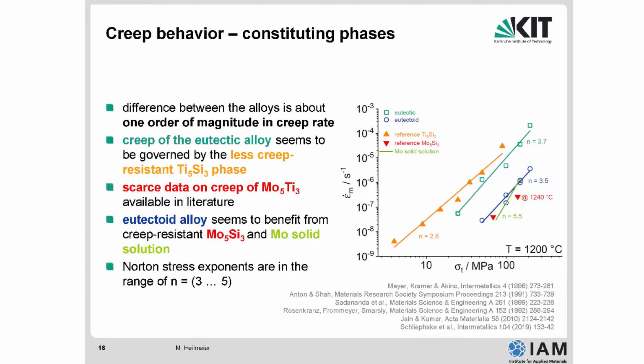Because in the green alloy, somehow the Ti5Si3 intermetallic phase is the major phase, and the green alloy obviously performs similar to the monolithic intermetallic compound Ti5Si3. Whereas in the blue alloy, the molybdenum solid solution and the Mo5Si3 are the constituents of this alloy, and as you can see here, the blue alloy shows exactly the same creep behavior as the molybdenum and the Mo5Si3. So you can understand why one alloy is better or superior to the other. And that's the main issue of this slide here.